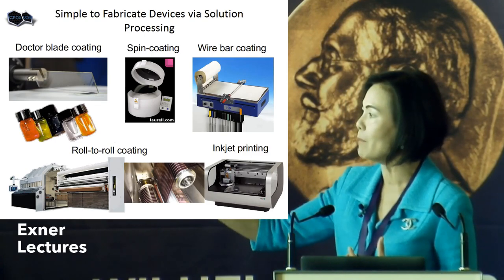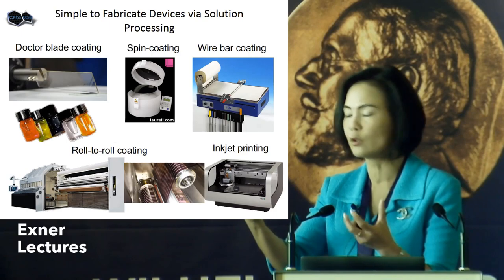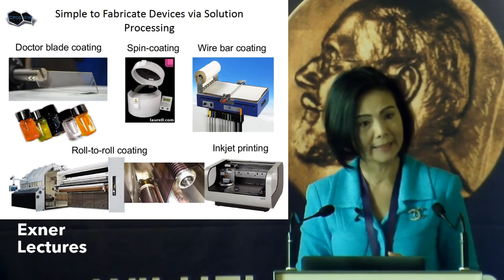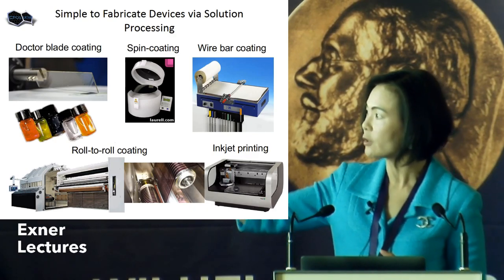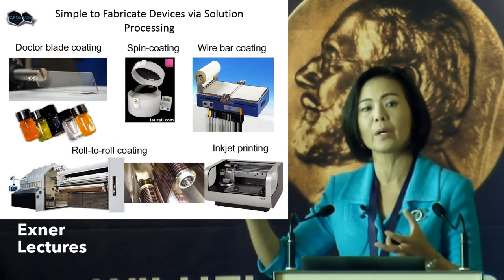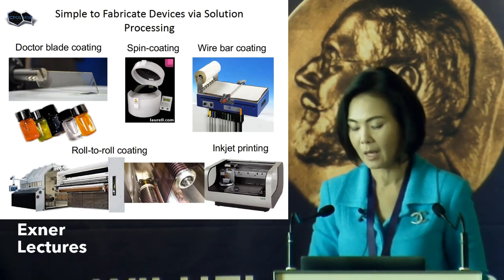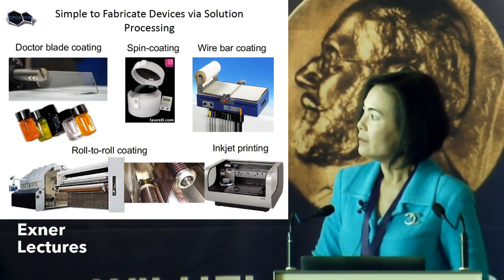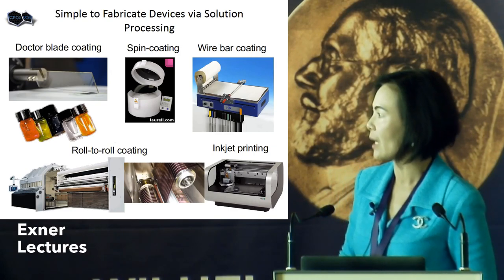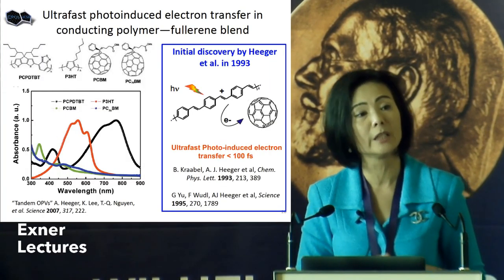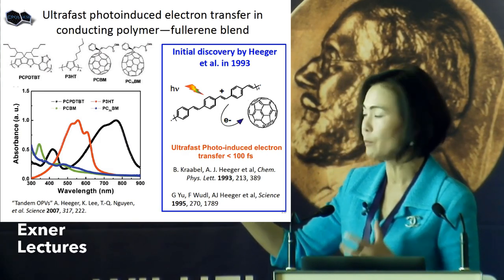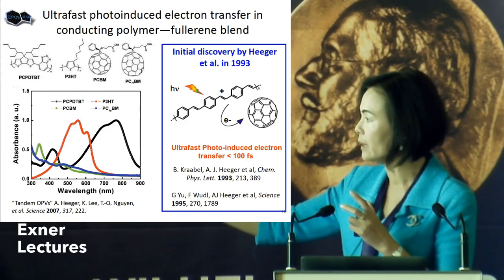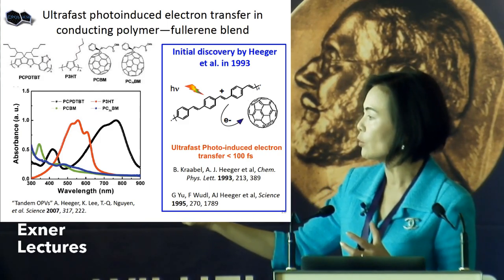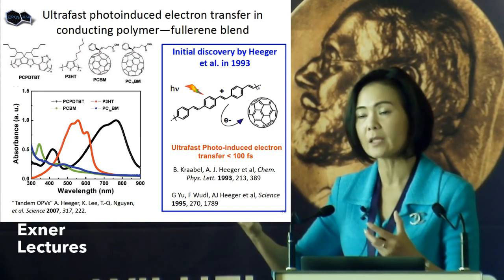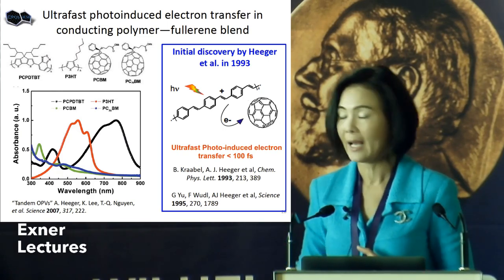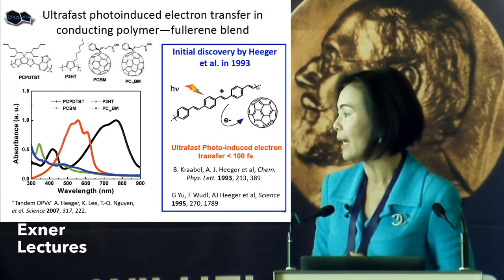So I show you here some different methods: you take the powder, dissolve it into organic solvent, you can form a beautiful colored ink, and then from there, you can use doctor blading, spin coating, wire bar, or inkjet printer, and you can print different sizes and shapes on flexible substrates. And the start of the organic solar cell actually began with the discovery by Alan Heeger and his colleague Fred Wudl, and they observed that if you take the polymer and blend it with fullerene, or the buckyball, and shine light on that, you see very ultrafast electron transfer from the polymer to the fullerene. And that was reported in the first paper in 1993 and then 2 years later in Science.